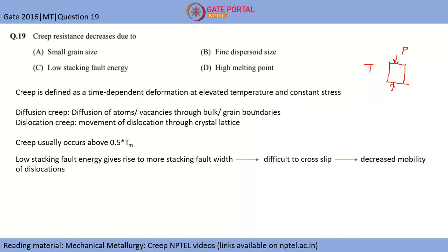And let's talk about low stacking fault energy. In dislocation creep, one dislocation is moving in a certain plane and has some hindrance, so it cannot move further. So it can cross slip to another plane and try to slide there. Using cross slip, dislocations move away from any hindrance and give plastic deformation by their movement. When low stacking fault energy is there, the stacking fault width is larger. If the stacking fault width is larger, it is difficult for a dislocation to cross slip, hence decreased mobility of dislocation. If mobility of dislocation decreases, creep resistance will increase, not decrease, because creep resistance comes from hindering the path of dislocations. Hence C is also not the option.